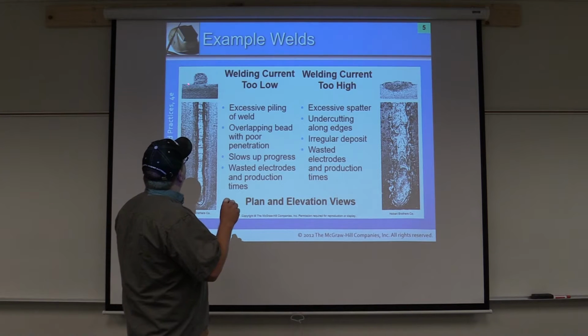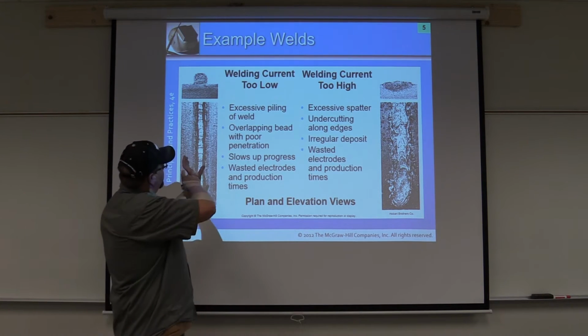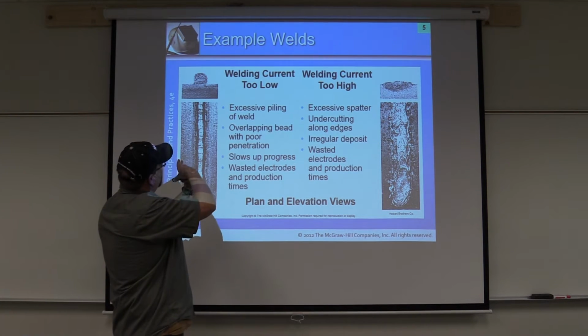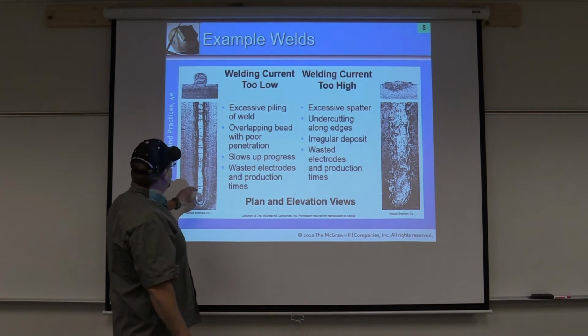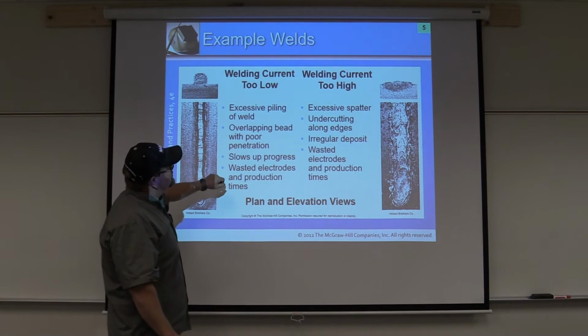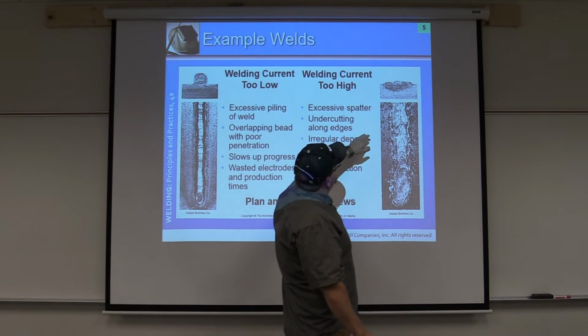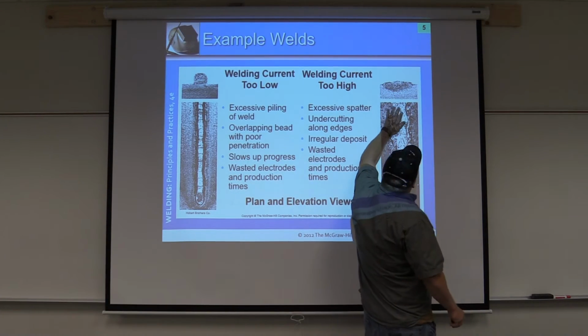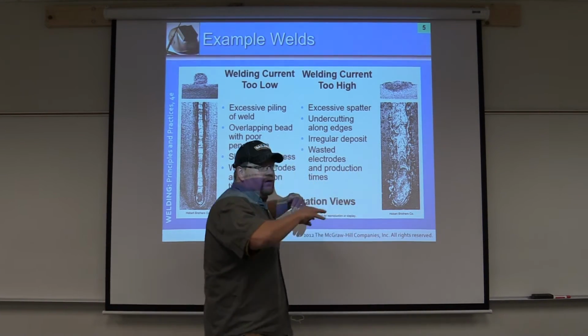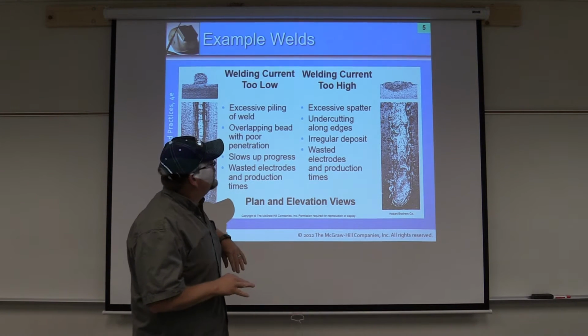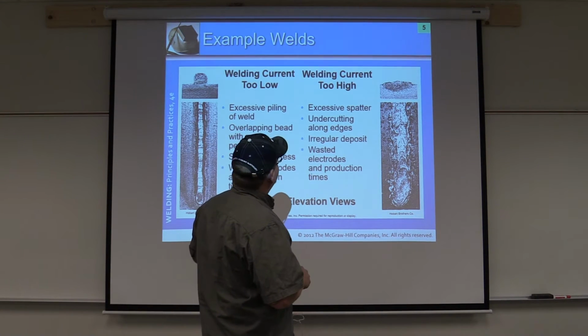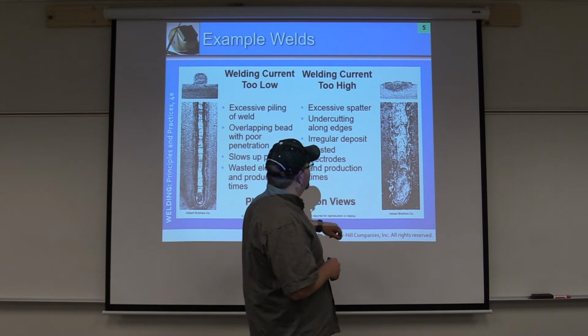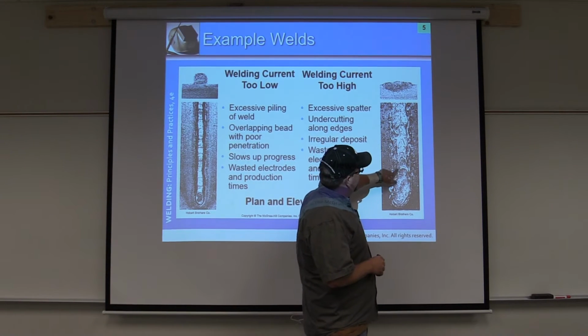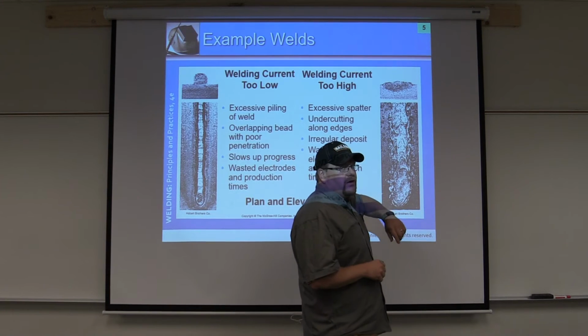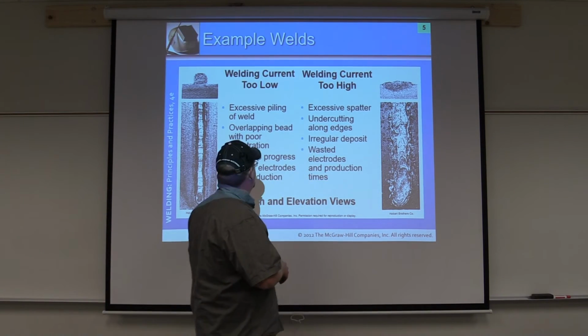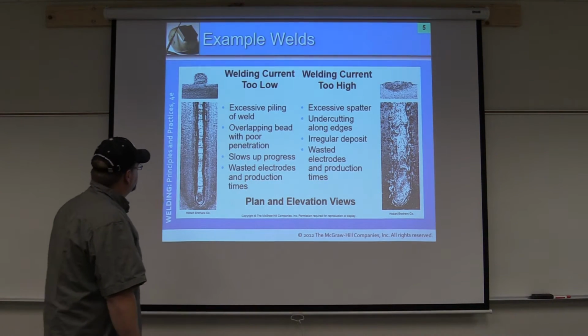So you notice how this weld profile is very tall and crowned over. Looks like it didn't get that great of fusion into the base metal and so forth. On this side, you can see that it's the exact opposite. It's really wide, very flat. So that's really high welding current. You know, we've got some V-shaped notches within our welding material. That also means we're going too fast, of course, with too high heat.